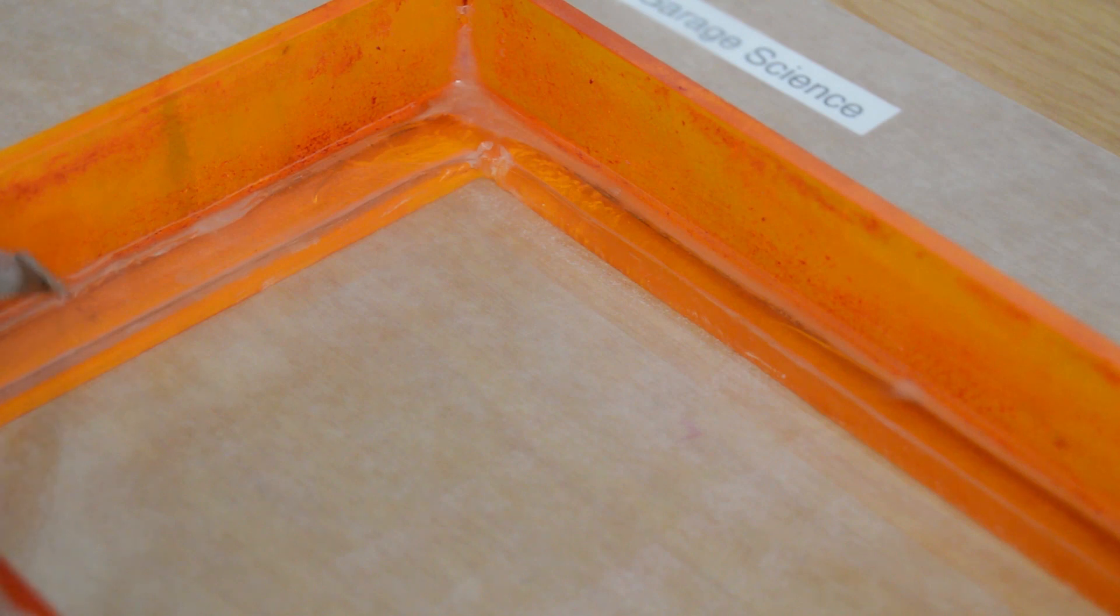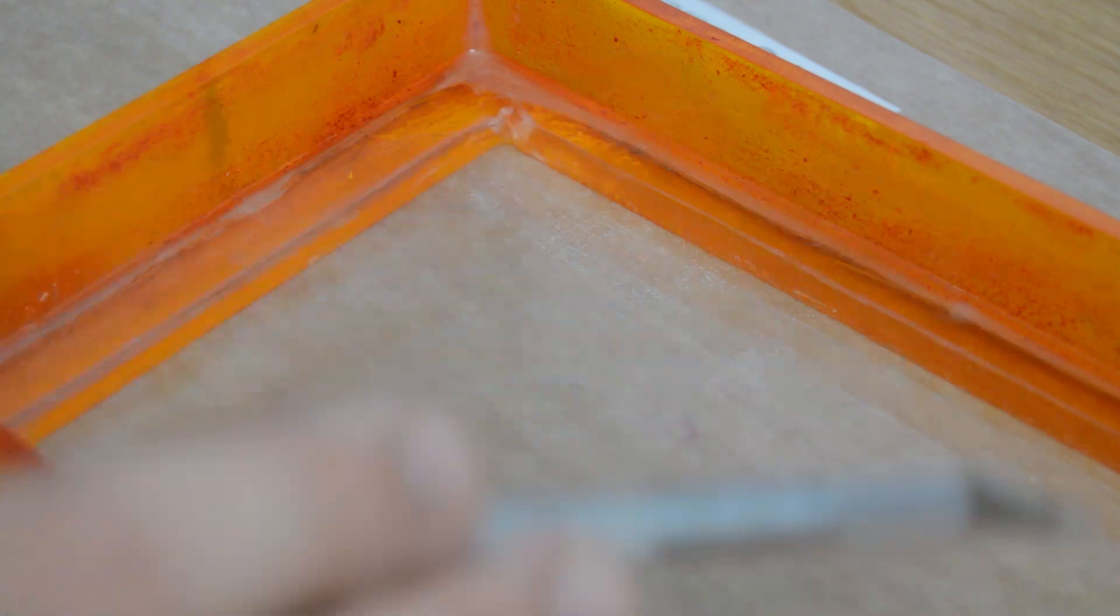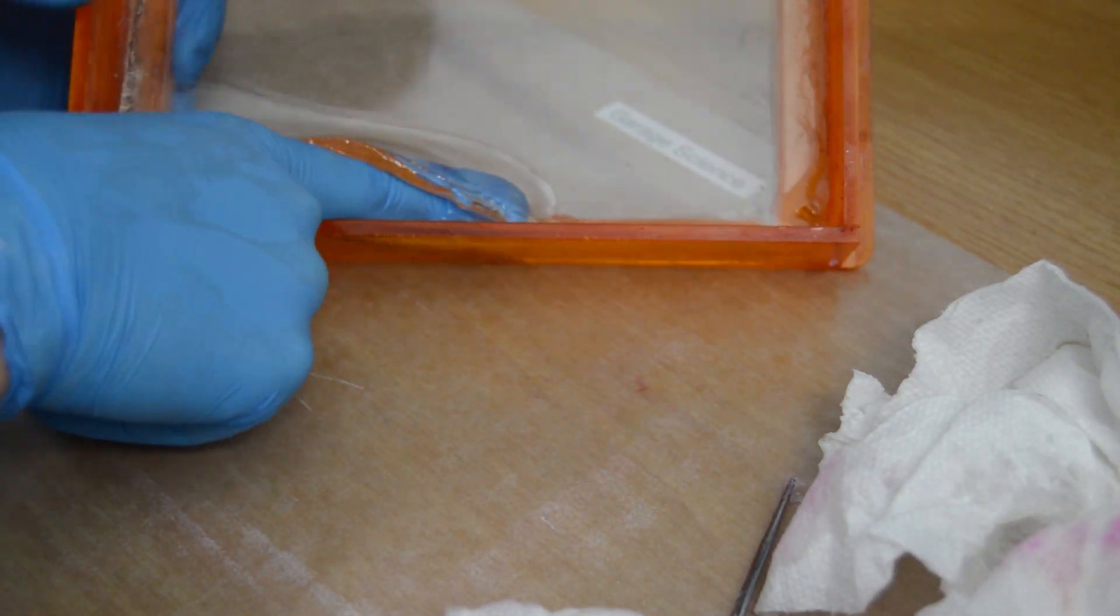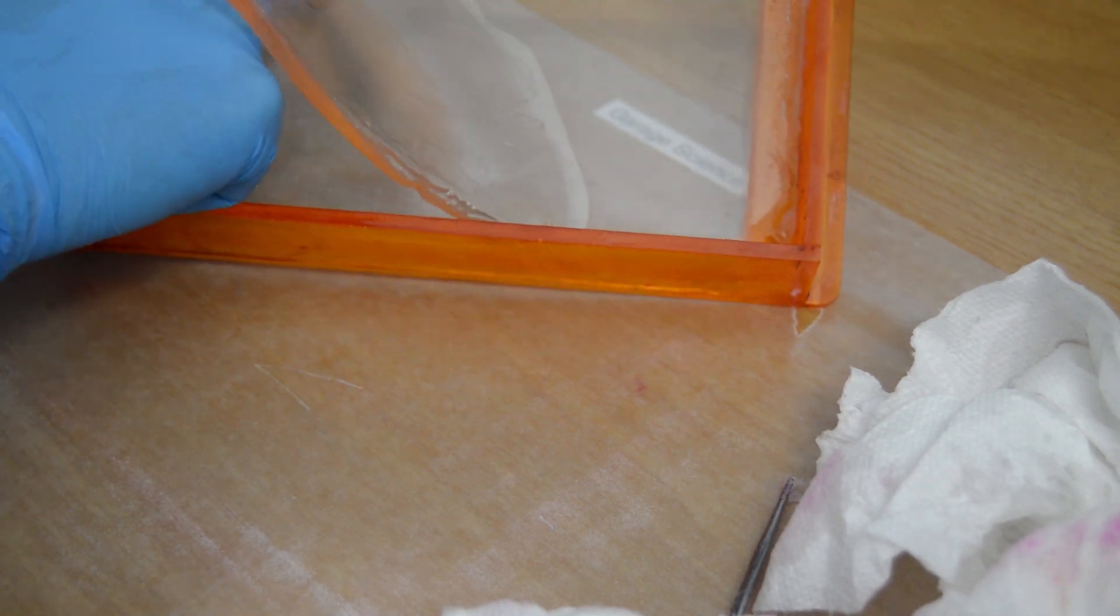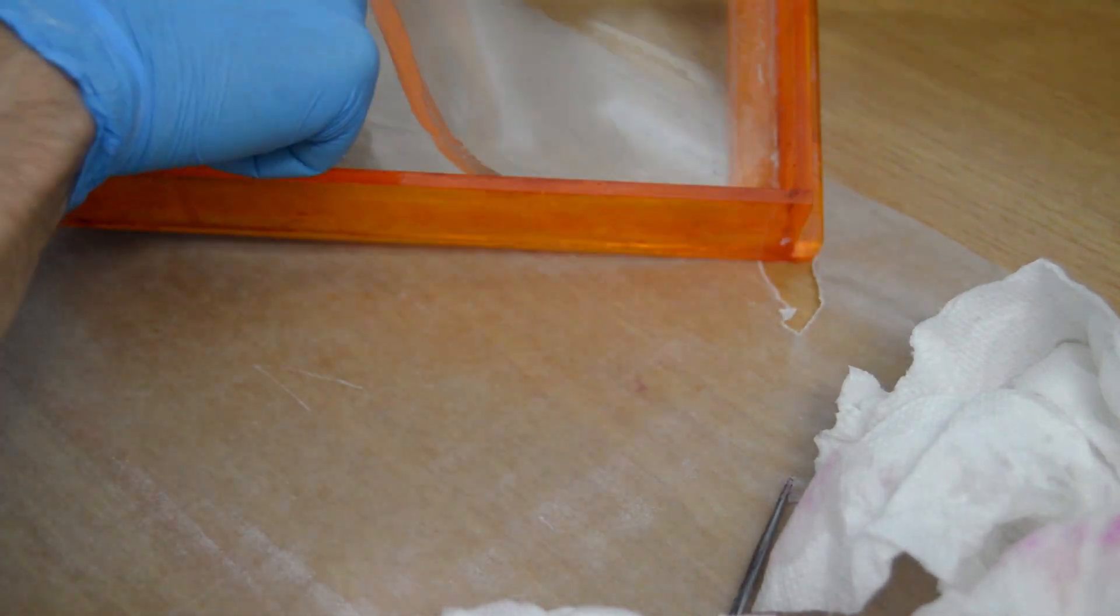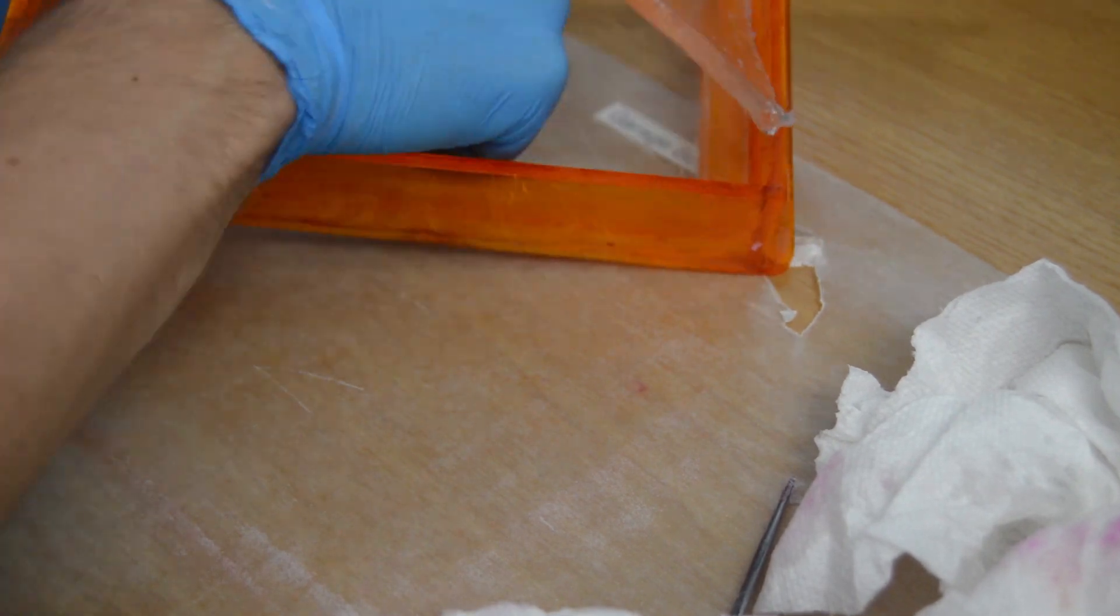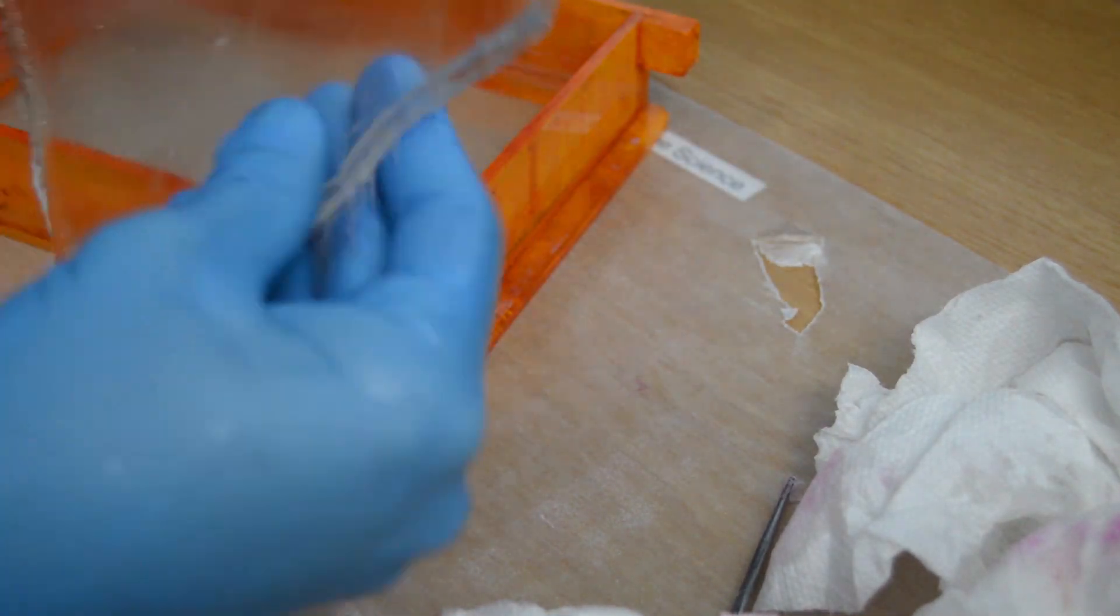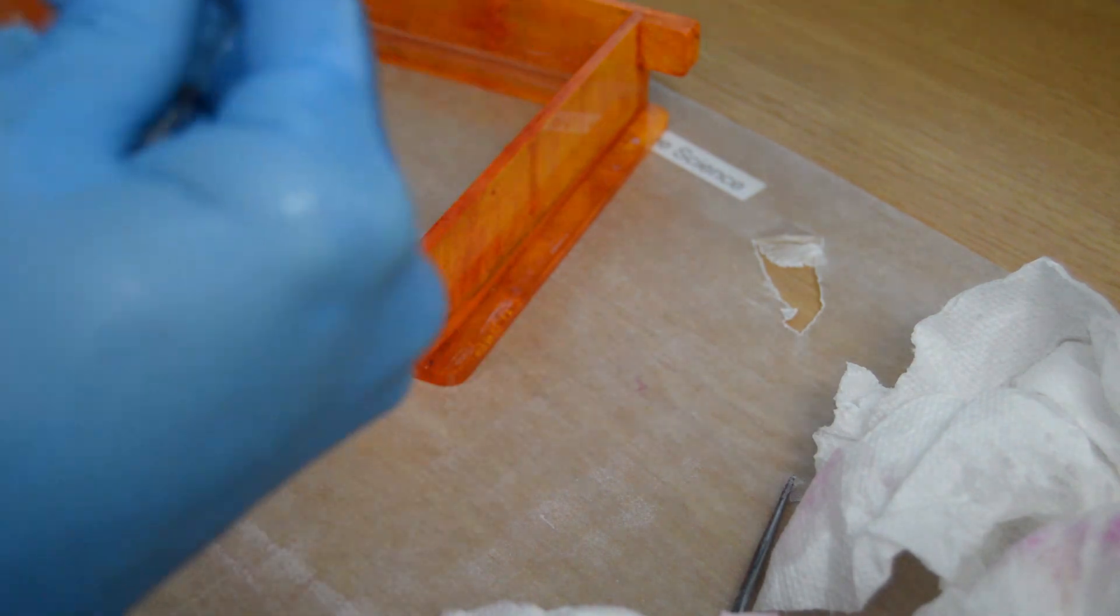And as you can see, the PDMS cured in the center of the vat, but not around the edges where the silicone was located. I attempted to recoat the edges with additional amounts of curing agent, but this did not cause them to cure, which sadly meant trying again. It's pretty aggravating when you wait several days on a project only to find out that something went wrong and you have to start over. So avoid being like me and don't use silicone on the inside of your vat.